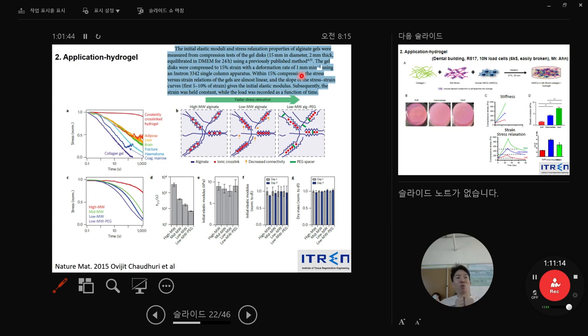So simply, when you check the mechanical strength of certain rubber material, when you stretch fast, your obtained value can be larger. But when you stretch slowly, the value is much smaller. So that is why mechanical people always mention the rate of compression or tension. Our instrument machine has a load cell, and the machine can move. So this rate is how fast they move, 1 millimeter per minute, or 10 millimeter per minute. Depending on this rate, you can get a very different value, okay?